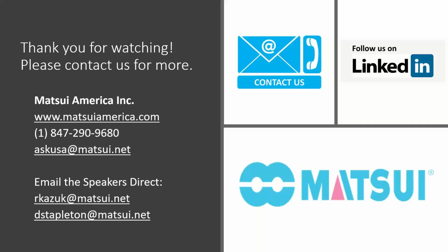As long as the discharge damper conveying times are set properly, there won't be any issues with the material reabsorbing moisture, unless it's an Isoplast material that's super moisture sensitive. But even our standard units have been used with that material. Again, as long as the settings are set correctly, it should be no problem. And the APH is completely enclosed. There's no open air.